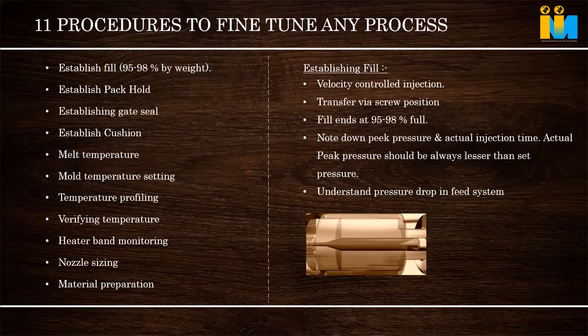Again I change to 3 seconds, I measure, it has increased again and the part looks better. But after some time, I increase to 4 seconds, 5 seconds, 6 seconds, and the part weight never changes. This means my gate has already sealed. So we have to understand that in that sealing time, if my part is not filled properly, then I have to increase the gate size, which is not simple, as it means changing the machine and all.